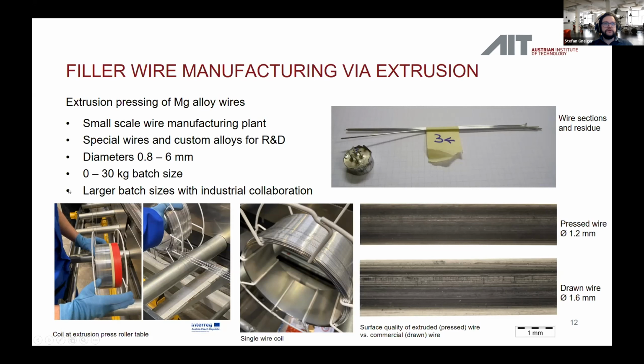Larger batch sizes can be produced with industrial collaboration, also using tailor-made alloys. Here you can see the single coil on the roller table of the extrusion press and a single wire coil. We produce this directly on the coils with an automatic coiling system, so that the material can be subsequently used in processing. Here you can see some wire sections and residue of the extrusion pressing process, here from a 20 millimeter container in the extrusion press, but we can also use larger scales for longer wires.